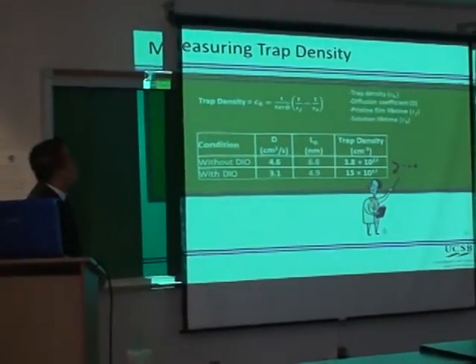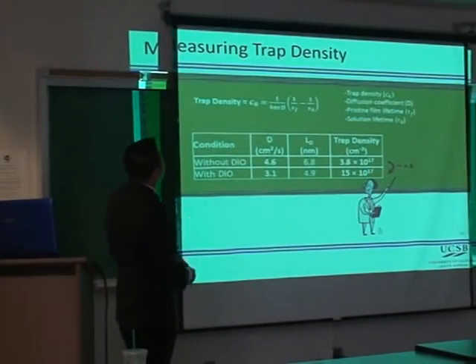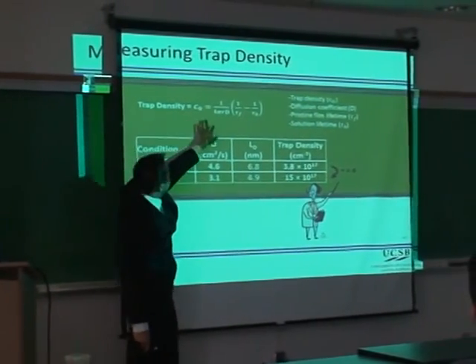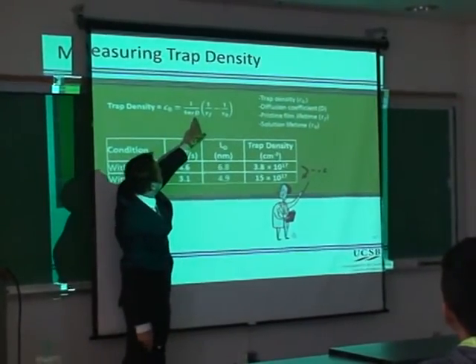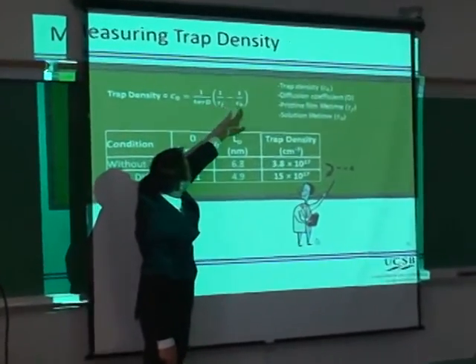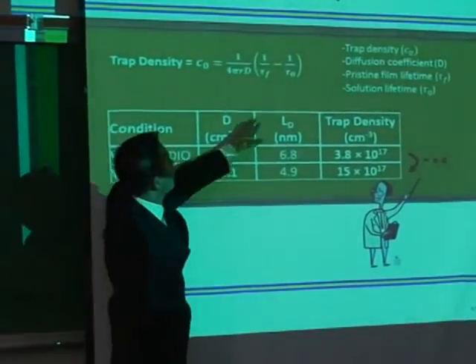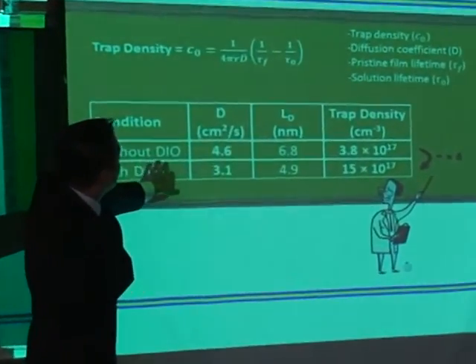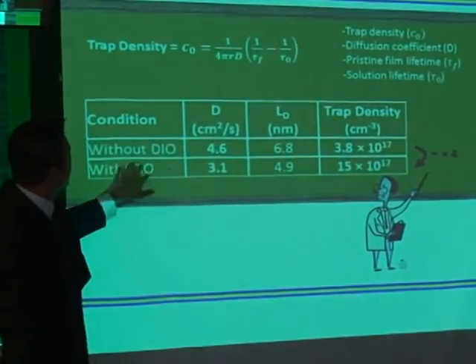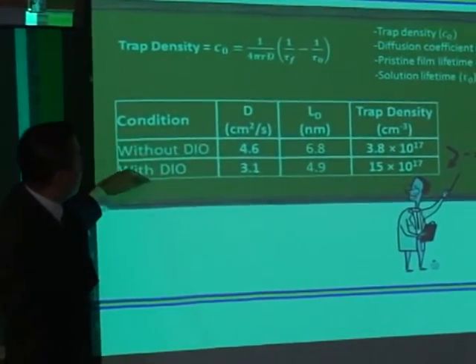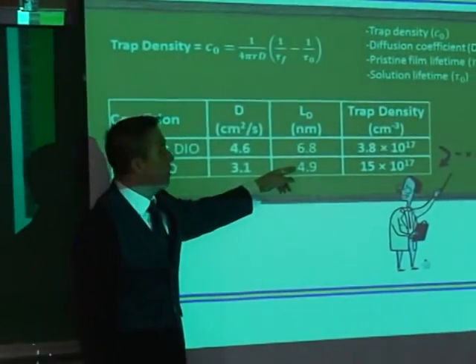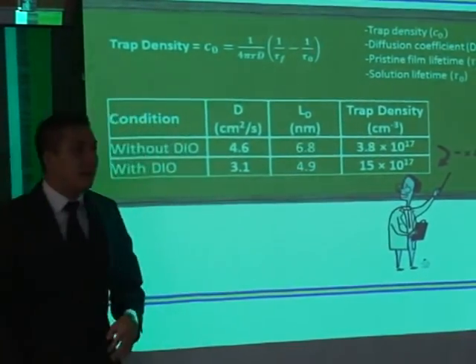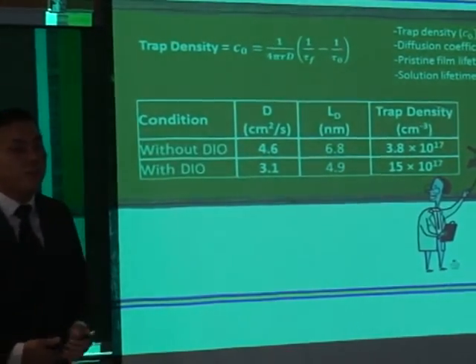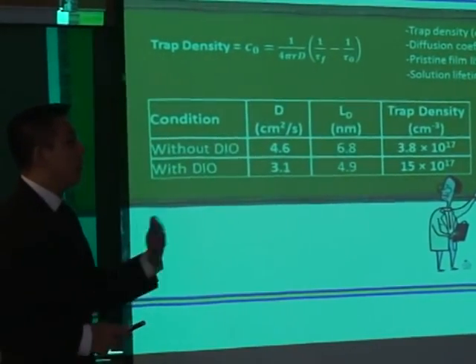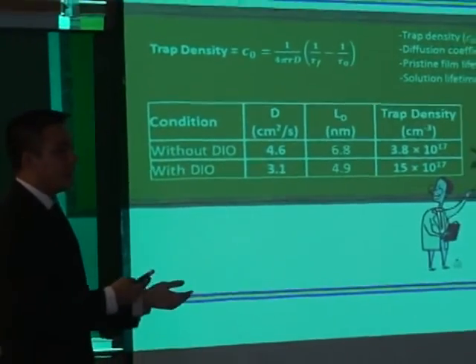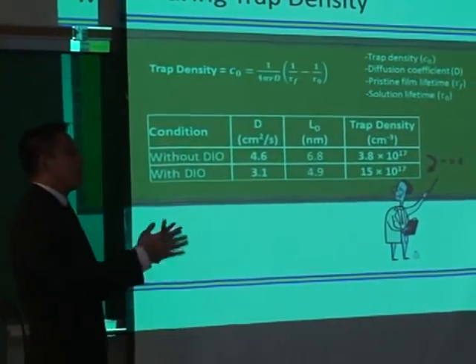In addition, in this study, we wanted to compare the trap density. So using this equation here, we just plug in the diffusion coefficient that we measured, the pristine film lifetime, and the lifetime without traps, which we can measure from the solution. And we can then calculate what the trap density is. What we find that's interesting is that when we add DIO, we have this decrease in exciton diffusion length from 6.8 to 4.9. And this is quite counterintuitive because we knew from previous studies that processing with DIO increased the crystallinity of the molecular ordering. So it contradicted our previous work and a lot of other works.